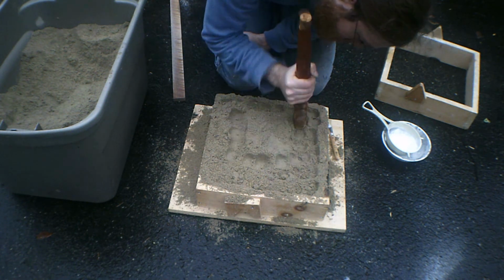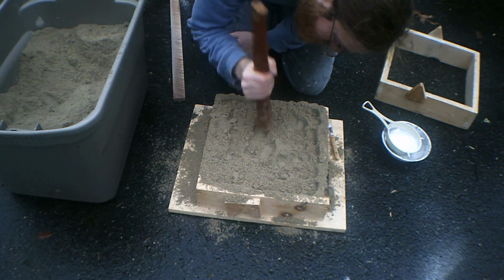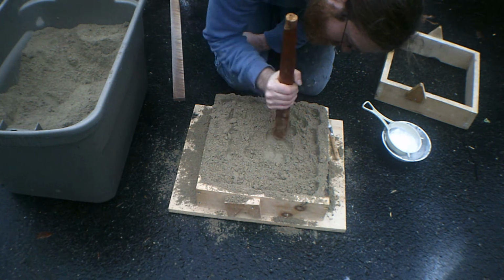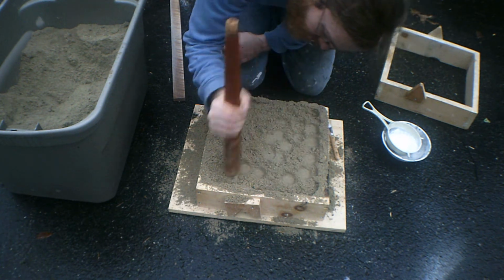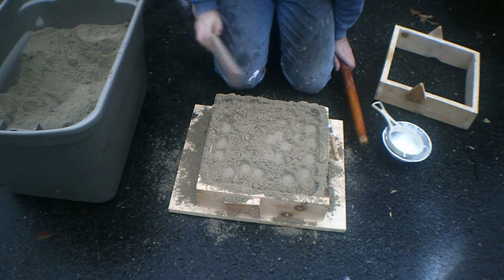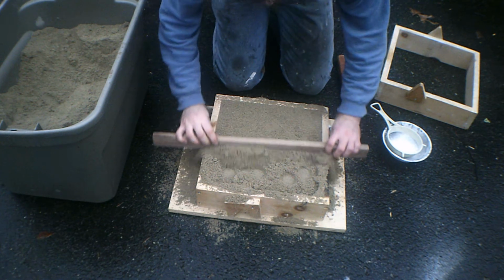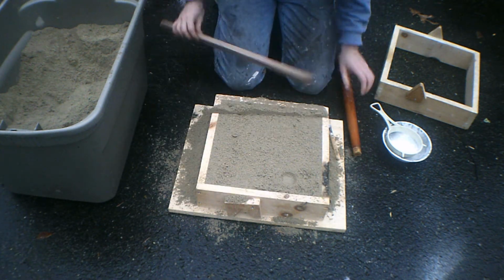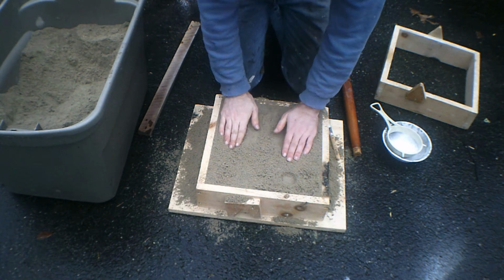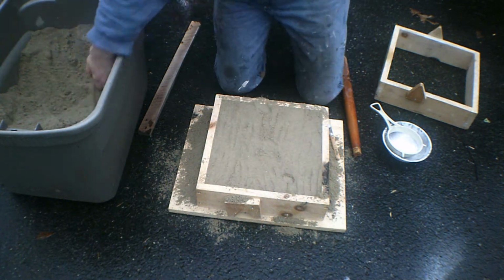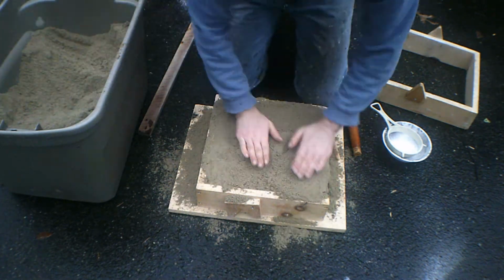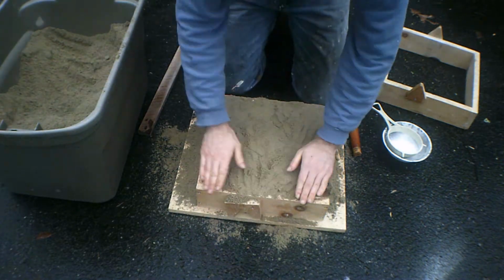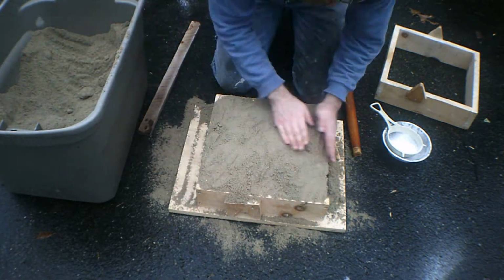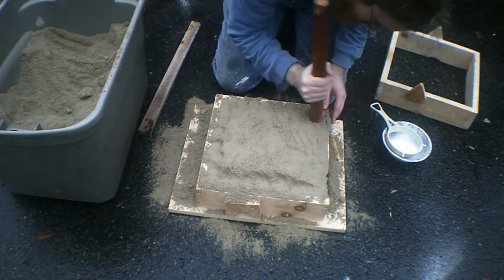You press it down very rapidly with strikes by the blunt end of the rammer to get the sand to actually hold its form. After you're done with that, you need to strike it off so that it is a flat surface. Obviously, when you strike it off the first time, unless you were very excessive with how much you filled the flask, there will be some remaining, so sometimes it takes 2 or even 3 iterations of filling up with sand, ramming it down, and then striking off again.